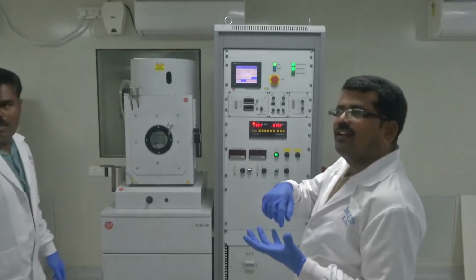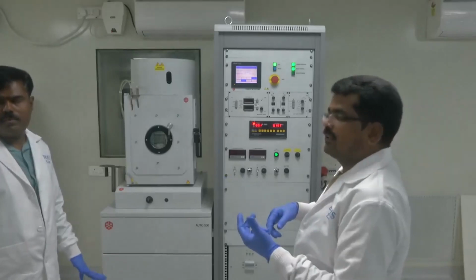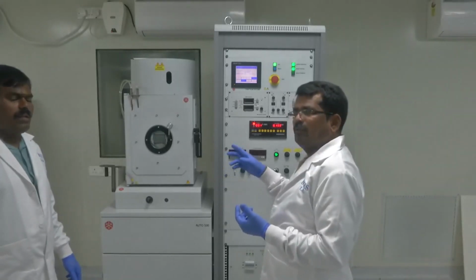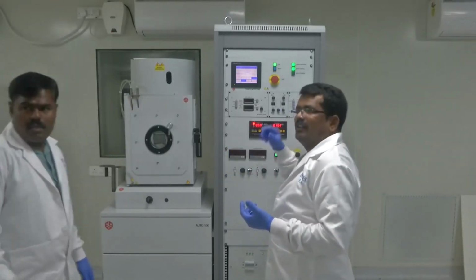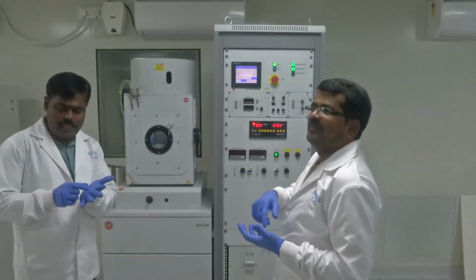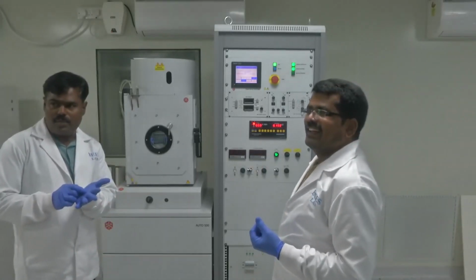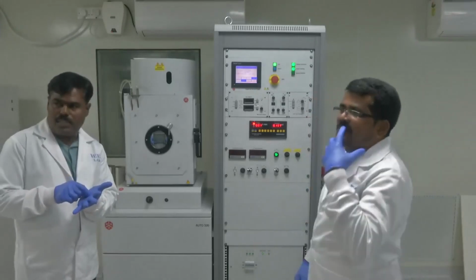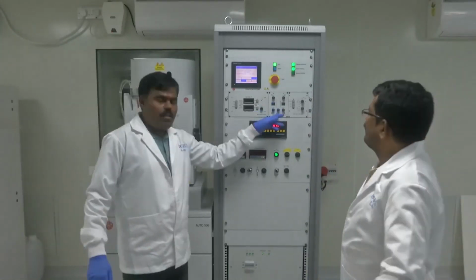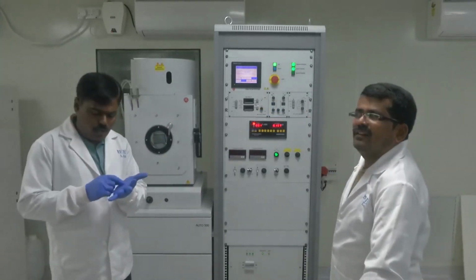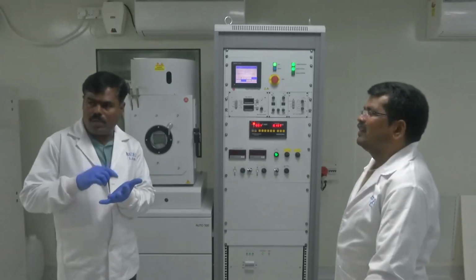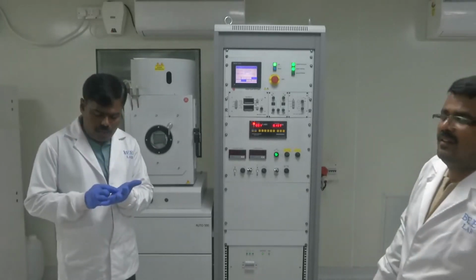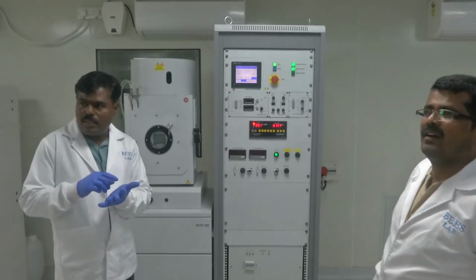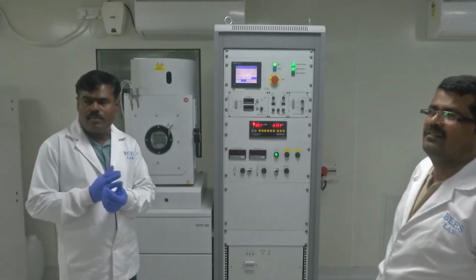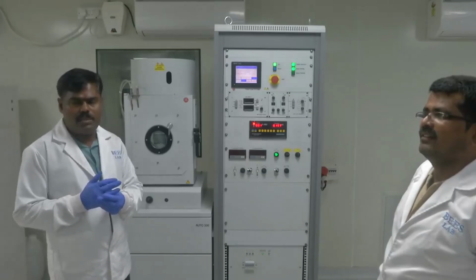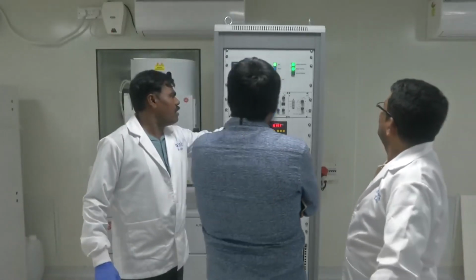But how do we know? Visually, you can see through the viewport and adjust again, adjusting X, Y and sweep, increasing the width. Initially it is 0, 0, which is the center. The beam has to cover the crucible fully, where your metal is to be evaporated, so you have to increase it a little bit. Beam dispersion can also be adjusted; you have to increase this.